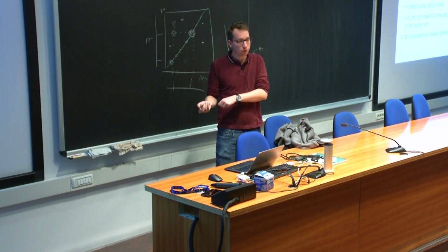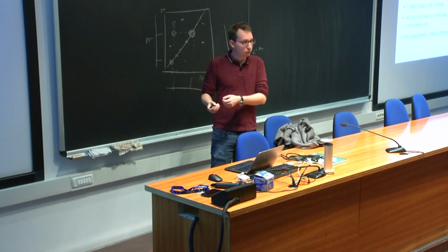I say this because of some materials like graphene and so on, where it is nice to see the dielectric constant, then you get stuck on this problem. And so either you do the calculation wrongly without the smearing, or you cannot do epsilon. So sometimes you know what you're doing. You just go in the code, you remove the check, you do it. But don't do it if the system is a metal. In that case, we get random nonsense, and it doesn't work.